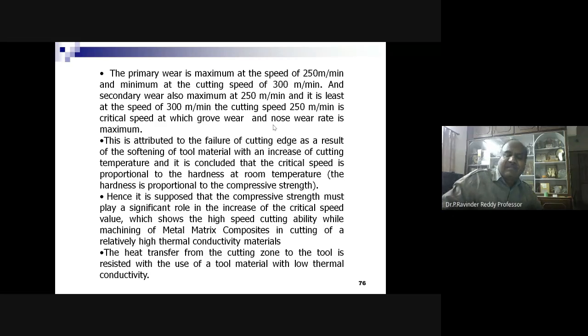The cutting speed of 250 meters per minute is the critical speed at which the groove wear and nose wear rate is maximum. This is attributed to the failure of the cutting edge as a result of softening of tool material with an increase of cutting temperature. It is concluded that the critical speed is proportional to the hardness at room temperature. The hardness is proportional to the compressive strength, as you know. Hence, the compressive strength must play a significant role in the increase of the critical speed, which shows the high speed cutting ability while machining metal matrix composites and cutting of relatively high thermal conductivity materials.